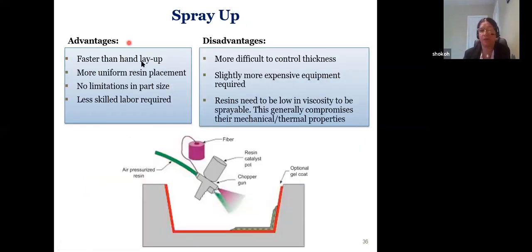The advantage of spray up compared to hand layup is faster, more uniform resin placement, no limitation on part size, so you can go to bigger sizes, and less skilled labor required if they are using a robot. It's more difficult to control thickness compared to other methods. It's slightly more expensive because of the gun you're using. The other important point is that the resin needs to go through the gun and spray, so you cannot use very high viscosity resin that doesn't flow easily. You have to use resin with low viscosity, and when you do that, you compromise mechanical or thermal property.